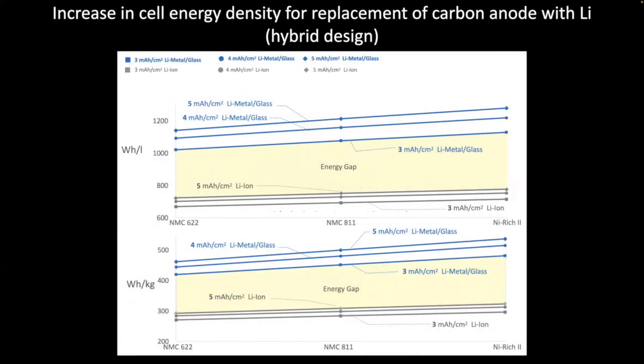And this is a projection of where we can take the technology as we move from graphite or carbon electrodes to lithium metal electrodes. That's basically the yellow gap you see there. That's the jump in energy density in that transition. And it's plotted as a function of your choice of cathode. The lithium glass doesn't really care what your cathode is. So as cathodes improve, you'll see the same kind of improvement going from graphite to lithium. So you can see a pretty substantial jump.